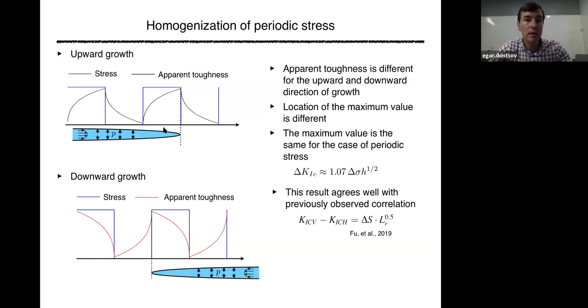And that's why you can see how these corrections for the upward and downward growth are different. That's why we need to introduce the toughness in a different manner above the wellbore and below the wellbore. But for the periodic case, when you homogenize, the maximum is still the same, right? But in general, if you use field data, they are not the same. I hope this gives you enough motivation to agree on this.